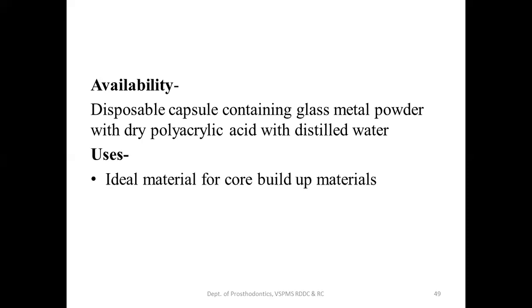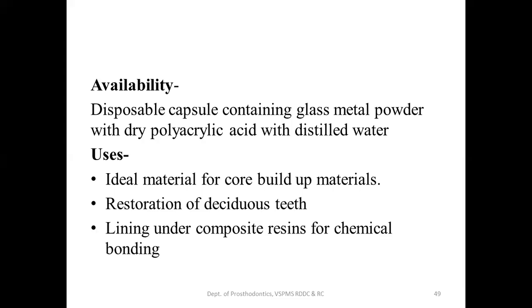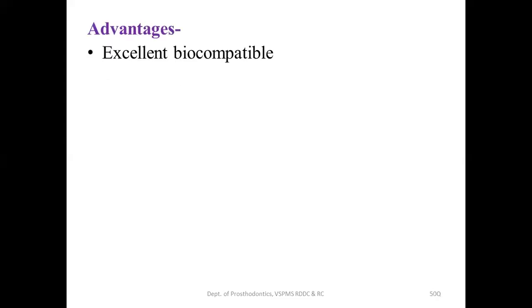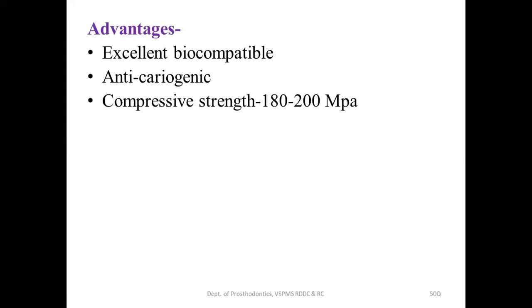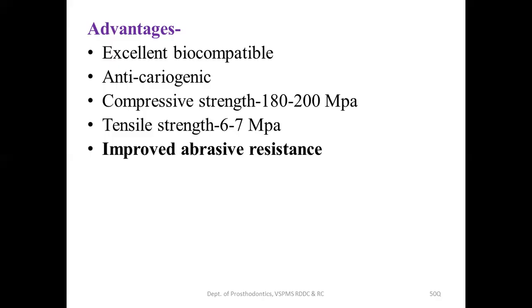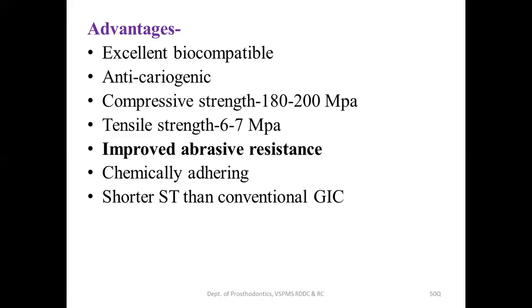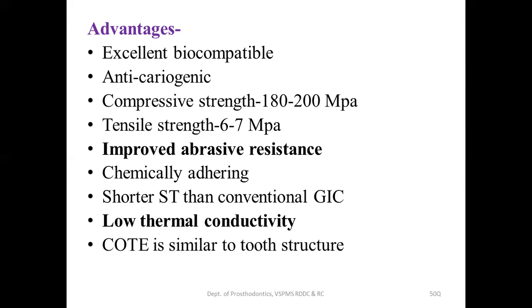The uses are: it is the ideal material for core build-up, restoration of the deciduous teeth, and lining under the composite resin for chemical bonding. The advantages are excellent biocompatibility and anti-cariogenic property. The compressive strength is quite high. The tensile strength is still less, but the abrasion resistance is improved in this case. It is chemically adhering, and it has a shorter setting time than conventional GICs, so it is good for the patient. Low thermal conductivity. The coefficient of thermal expansion is similar to the tooth structure.